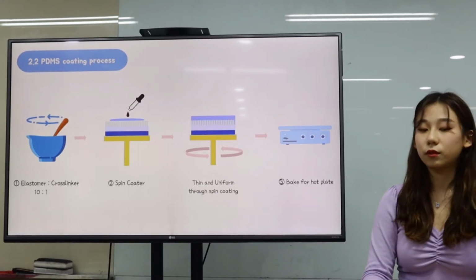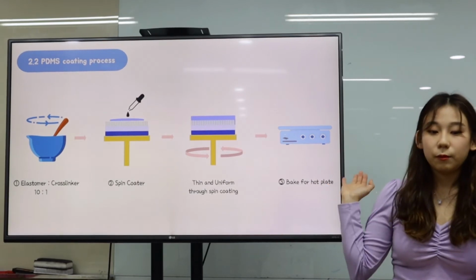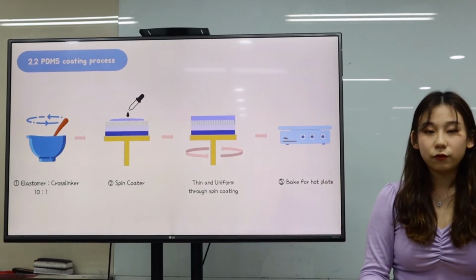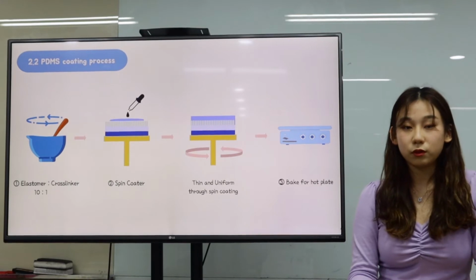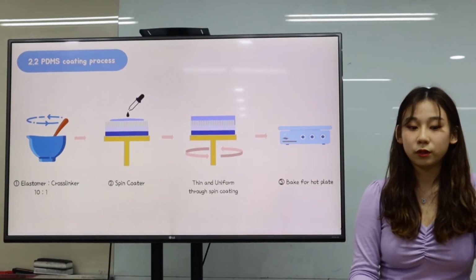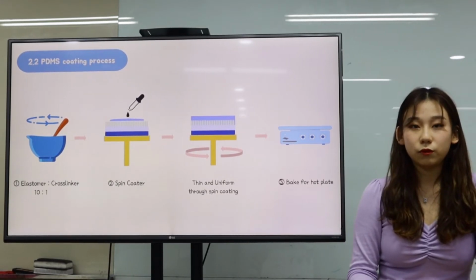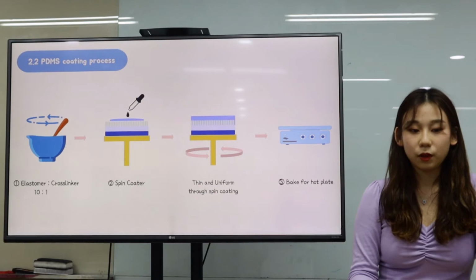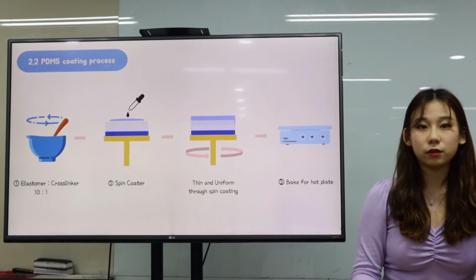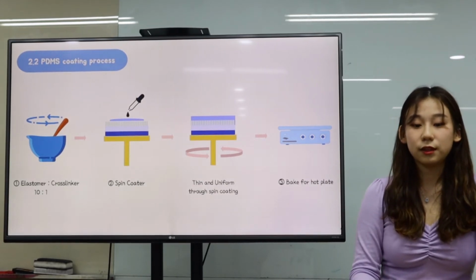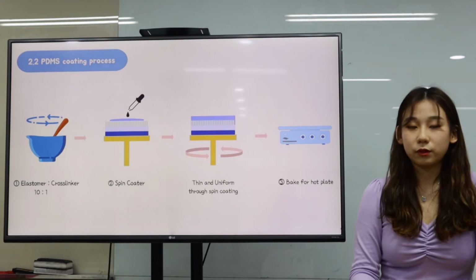Number 3, PDMS coating process. First, mix elastomer and cross-linker with a 10:1 ratio and remove the bubbles. Second, we use a spin coater to spread it uniformly. Third, to erase the stickiness, bake on the hot plate for 7 minutes.